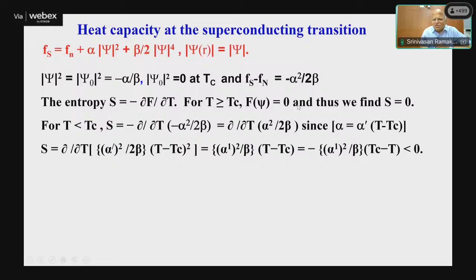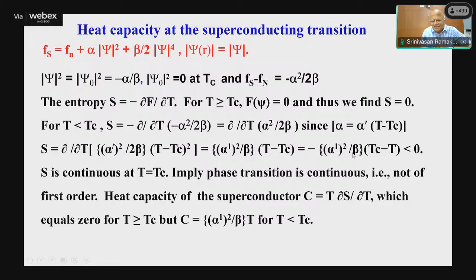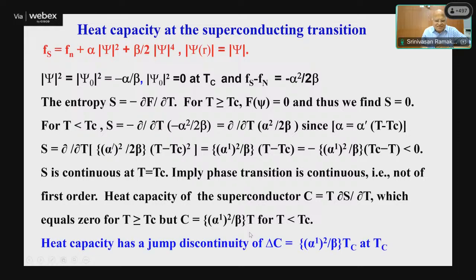So when T is greater than Tc, it is zero, so we find that there is no entropy associated. But for T less than Tc, you can see that there is a finite entropy value, and that is given by this expression. The final expression is this. So S is continuous at Tc, which implies the phase transition is continuous, not first order, it is second order. The heat capacity of the superconductor equals 0 for T greater than Tc, but it has a finite value for T less than Tc. So one can show that the heat capacity has a jump of this value at Tc.